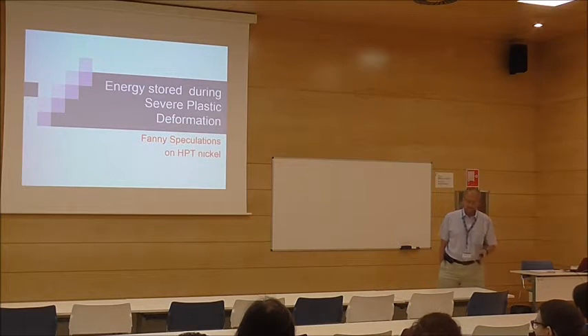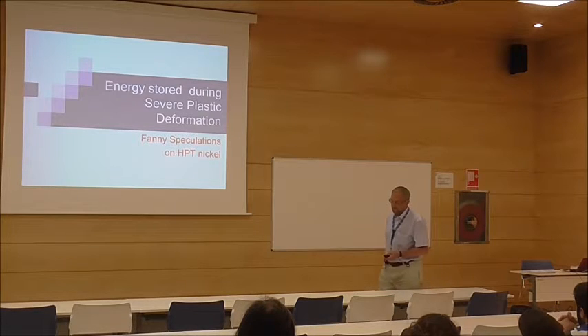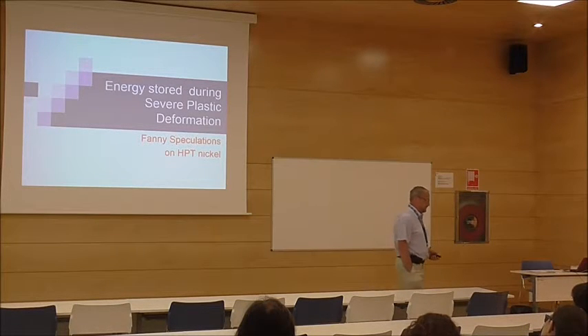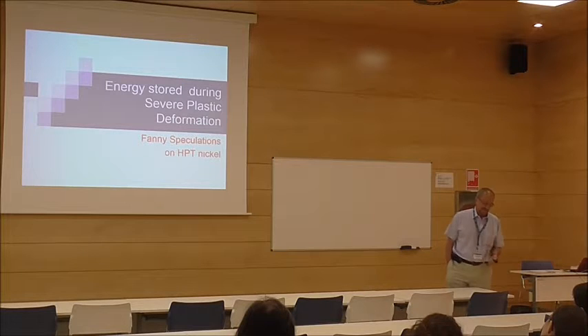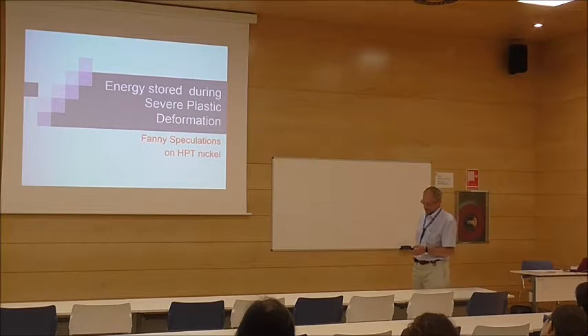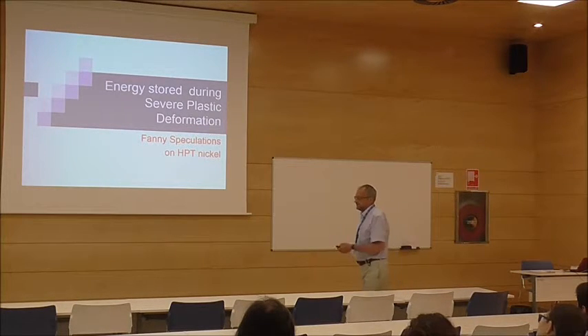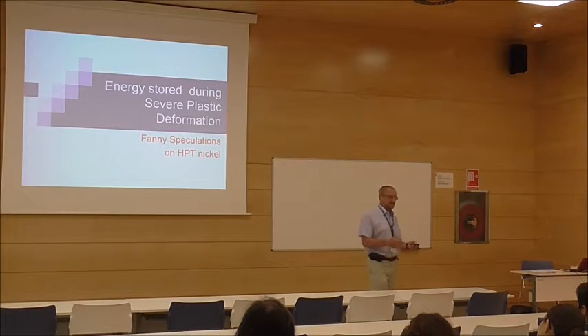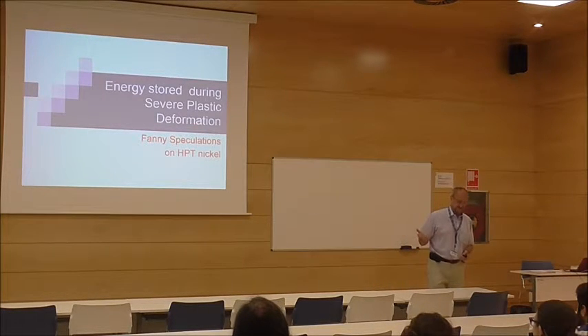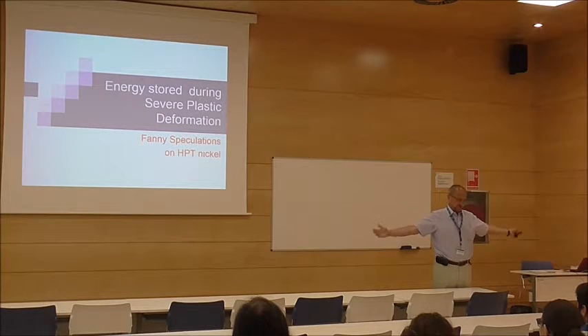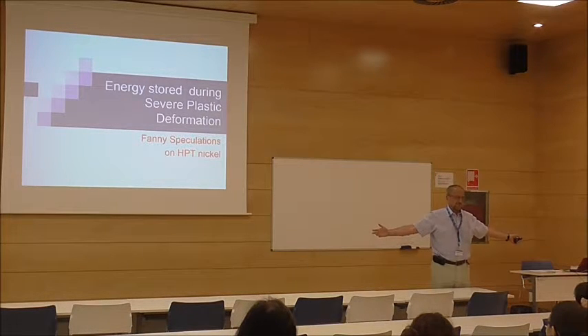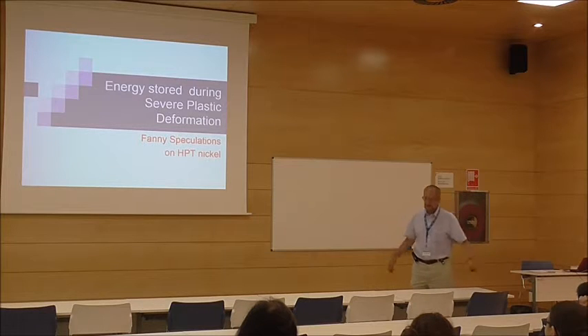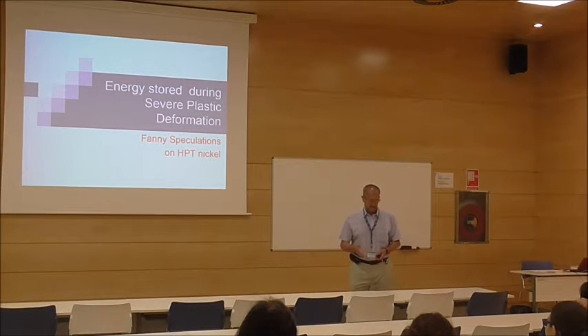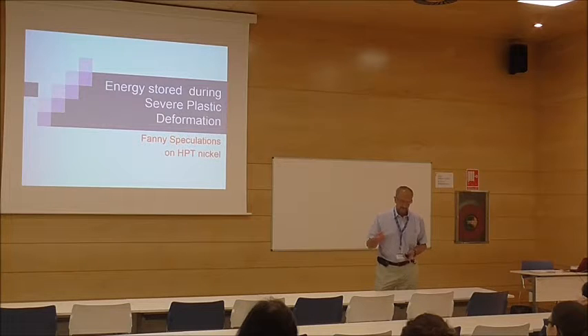Of course, any calculation is incorrect because it was developed for small actual strain compared to HPT. But anyway, when we calculate equivalent strain, you have to think: if you calculate equivalent strain with von Mises, that means you put so huge a strain in the material that, when you multiply with the applied stress, you will get so huge an energy induced into the material. When you calculate this value, it's incredible.